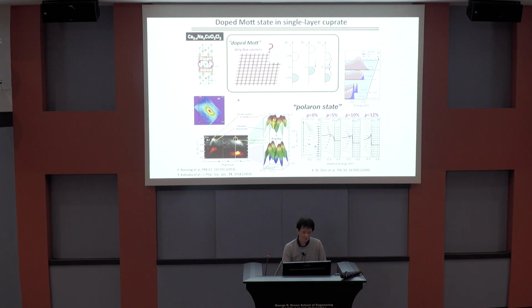Then, even though you expect the formation of a small Fermi pocket, actually only part of the Fermi arc is observed by ARPES. It's also found that to generate a well-defined quasi-particle, you need a doping level of more than 10%. At less doped levels, a huge incoherent part appears, so you can say it's a polaron-like state in this lightly doped region.